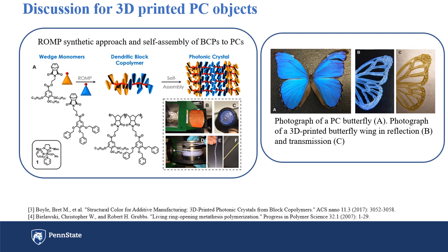To get around this fundamental problem, the design and synthesis of macromolecules with rigid rod characteristics is necessary to reduce the capability for chain entanglement, which can allow for rapid self-assembly to PCs. Molecular brush and dendritic copolymers composed of sterically bulky repeat units can limit the potential for chain entanglement and have been successfully synthesized by an approach called ring-opening metathesis polymerization (ROMP).